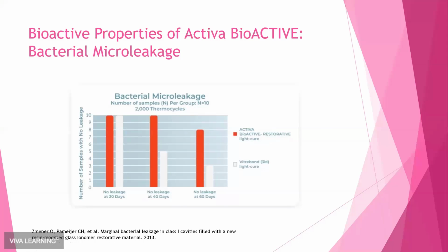So it's probably not surprising after the last slide that we're seeing less bacterial microleakage with the Activa material. So this study compared it against Vitrebond light cure material, and you can see that at 20 days, there was no bacterial leakage from either material. At 40 days, the Activa was still not exhibiting any bacterial microleakage, whereas the Vitrebond was. And then at 60 days, we start to see some bacterial leakage, but still excelling over the other material. So I think as a clinician, these are all important things to have a general knowledge of and to consider when you're choosing material to use for your patients.